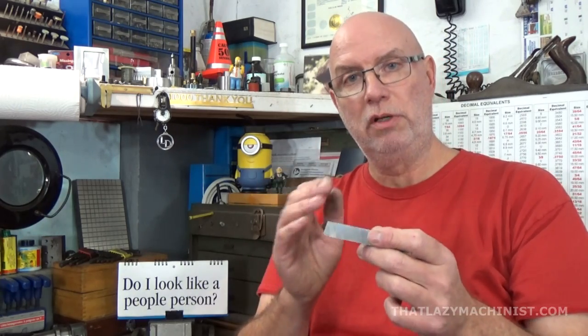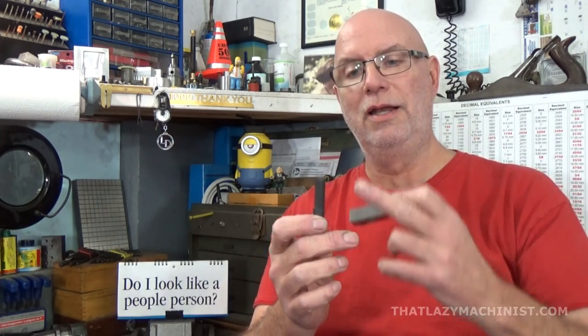Now, if I measure this D-shaped hole from one end to the other, I notice that I have a 6/1000th of an inch difference between the starting side and the end side. And why is that? Well, it's not a gradual taper. The hole is generally parallel, and just at the very end, it sort of rounds out in the last quarter. That's because our electrode cuts mostly on its end, but also slightly on its side. And as that side starts to wear, it rounds off the end of the electrode slightly, and that's what gives me the difference in diameter.